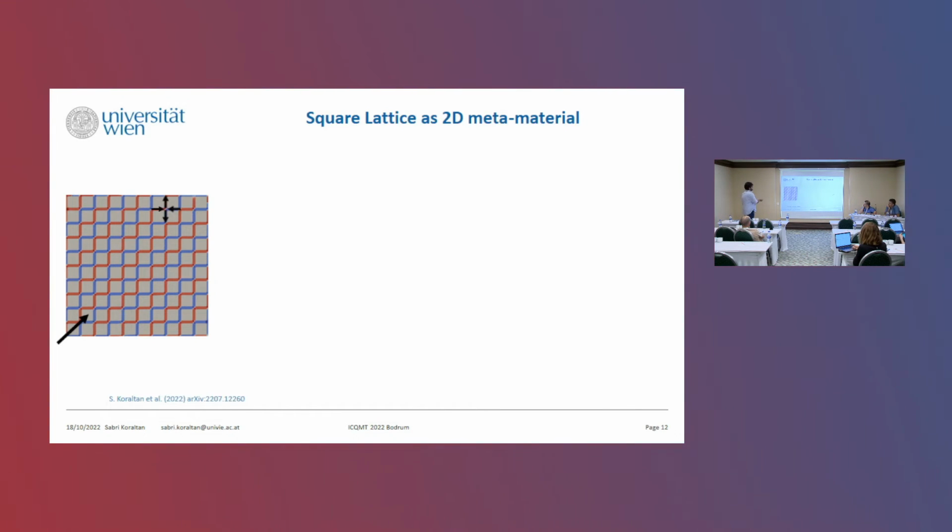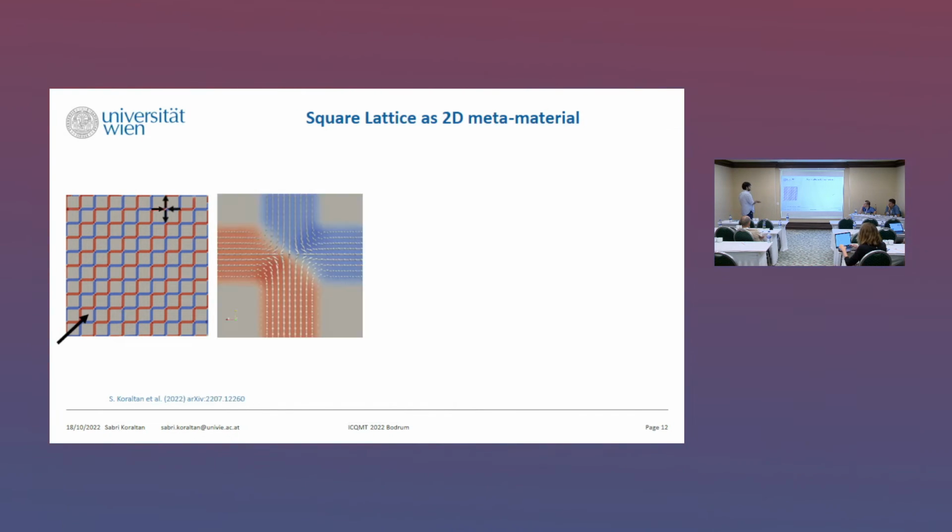And in this case, we build the closed loops, and that's why we have the long range or the ground state. But in spin ice and artificial spin ice field, people do not use interconnected lattices, but rather stadium-shaped islands and so on. But here we have the interconnected system. So whenever we have this structure, the magnetic configuration is then forced to build an anti-vortex.